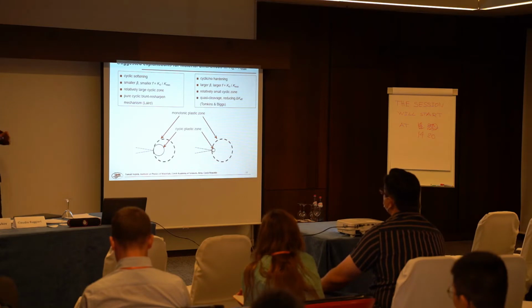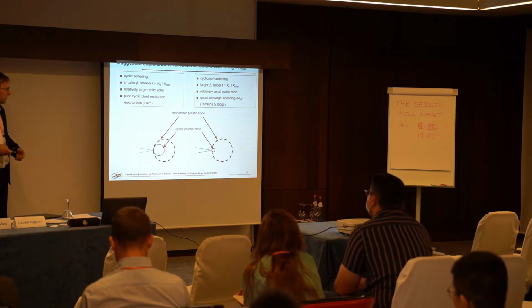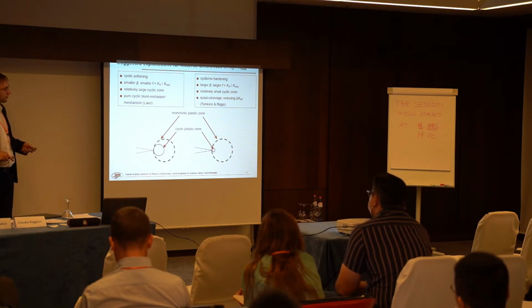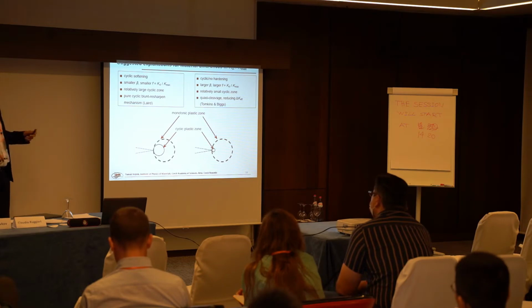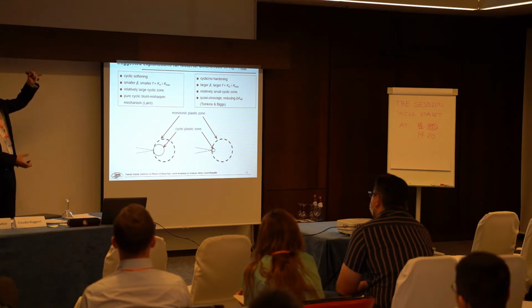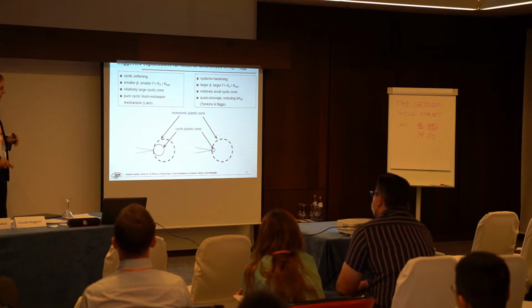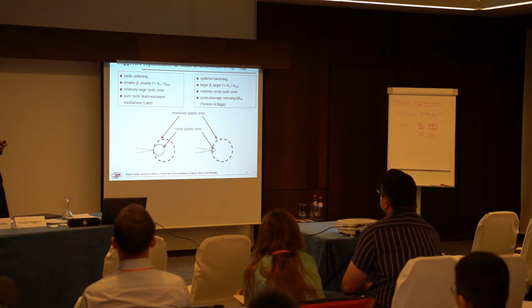And plasticity induced crack closure is proportional to the size of the monotonic zone. But when we think about two different sizes of the cyclic plastic zone, this also has effect on plasticity induced crack closure. It has the opposite effect. If we have larger cyclic plastic zone, we have less plasticity induced crack closure. Because obviously in the monotonic plastic zone you stretch the material, and then there is a wedging effect in the crack wake. But if you have large cyclic plastic zone, you partially compensate the effect. So according to the behavior of the material, if it's cyclic softening or hardening, we have different ratio between the sizes of the monotonic and cyclic plastic zone. And this is what we can relate to the constraint factor beta in compression.